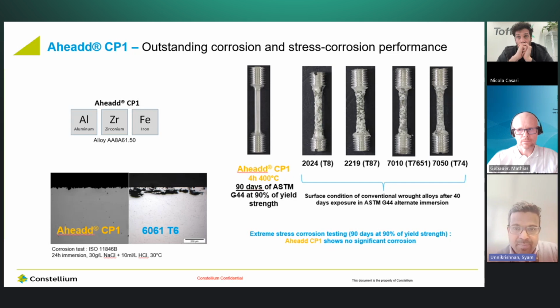Also, when the material is exposed to stress in a corrosive environment, CP1 also provides very good stress corrosion performance. For example, you can see on the top right-hand corner, Aheadd CP1 heat treated 4 hours, 400 degrees. Even after 90 days at 90% yield strength applied, you don't see a sign of corrosion attack. Whereas the aerospace grade alloys like 2024 or 7 series alloys are almost completely corroded in this extreme condition. So if you have an application that is exposed to a very corrosive environment, CP1 could be the clear winner.